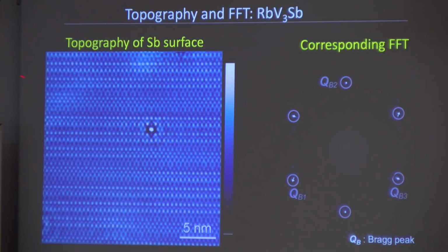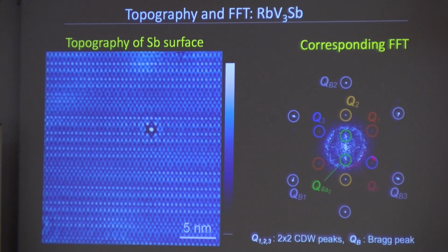So here's our data. This is the topography. These are the 6 Bragg peaks, and then right inside are the 6 CDW peaks. And inside is quasi-particle interference. I talked about this yesterday. I'm not going to talk about this at all. I'm going to basically mask the center so you don't see the quasi-particle interference. And I'm just going to focus on these 6 charge density wave peaks. And when necessary, I'll show you the Bragg peaks as well. You'll see this is really interesting.